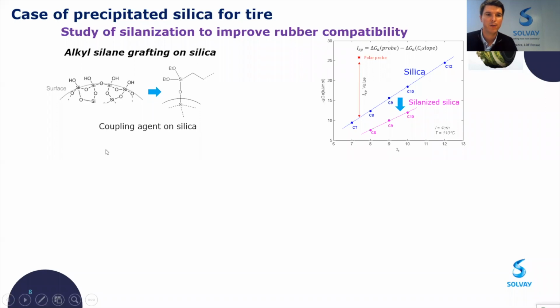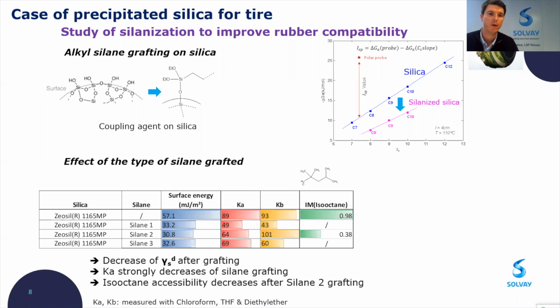Now, another study concerning the silanization of a silica used to improve the compatibility with rubber. It's well known in the literature, this kind of study, and we use it also at Solvay to try to compare the different types of silane at the surface and see the effect on the surface energy, Ka and Kb, and also the morphology index. And we try to correlate with the surface energy estimated for elastomer to see if we have some compatibility with this kind of materials.